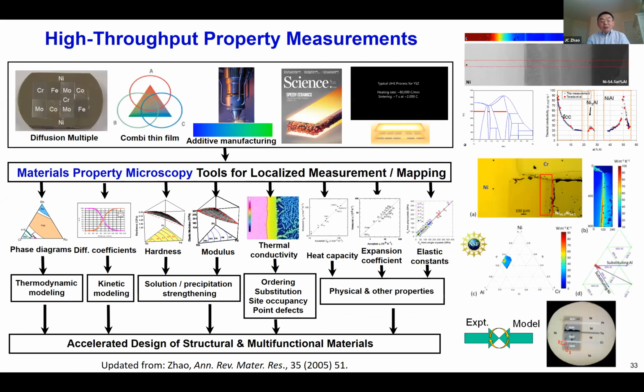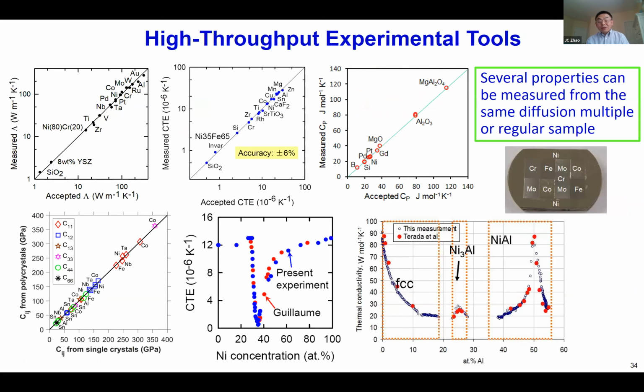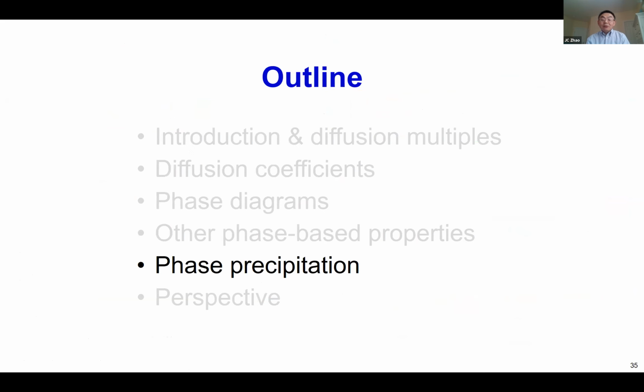Other properties: we developed tools to be able to measure properties locally at micron spatial resolution. So we can very quickly establish property databases from such measurements and compare with the individual measurements. You can see in this case, the red dots are individual measurements. We can map it out in ternary systems. We have developed tools for thermal conductivity, heat capacity, expansion coefficient, and elastic constants. And all of them can be measured in the same polished sample across the same composition gradient. So these are extremely effective tools.